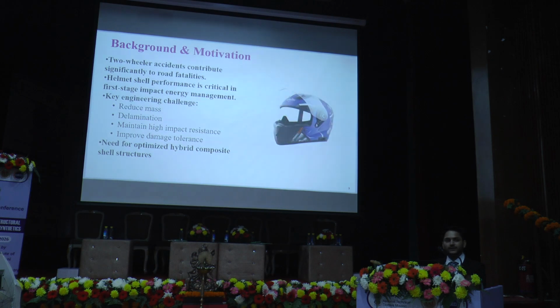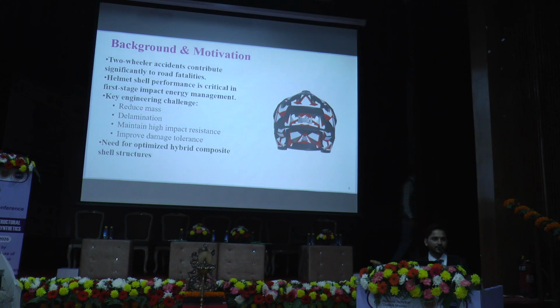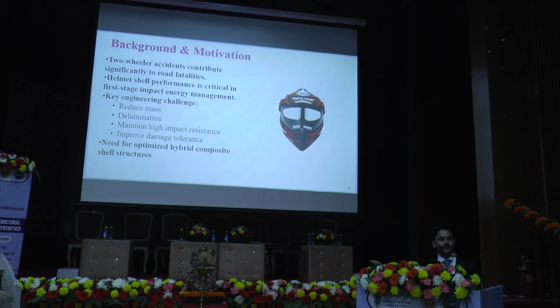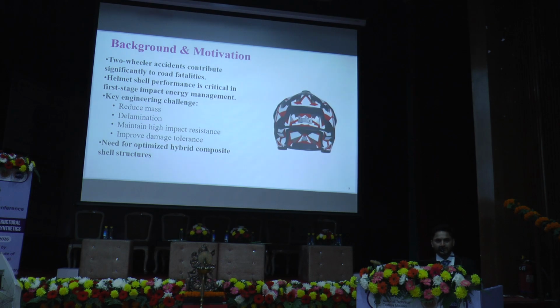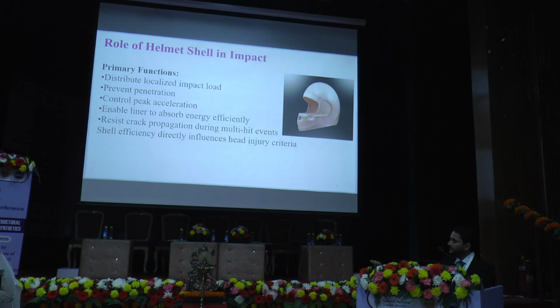For the helmet shell, there are basically two processes of development. One is the fiber reinforced composite shell and the other is the injection molded polymeric shell. I am concerned here with the fiber reinforced composite shell, because in a plastic molded helmet shell, to maintain that particular standard, the thickness is like 3 to 4 mm. In a fiber reinforced helmet shell, the thickness can be reduced up to 2 mm, and we also get high strength and low weight composites. This is the role of the helmet shell, as I already mentioned: distribute the localized impact load, prevent penetration and control the peak acceleration.